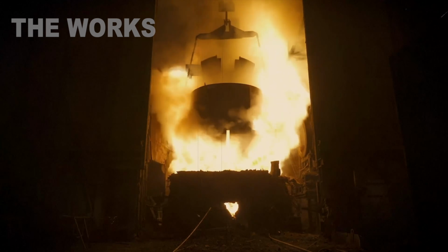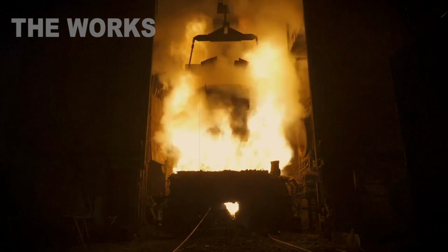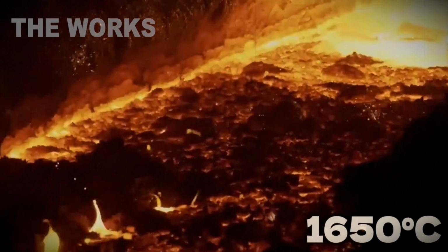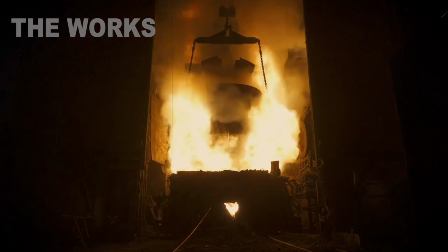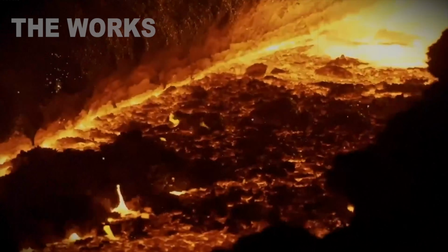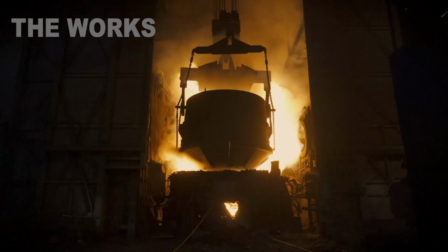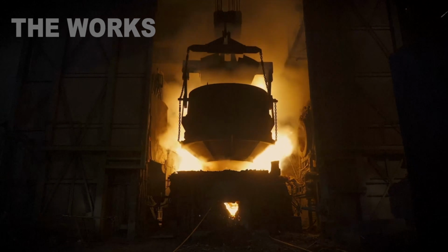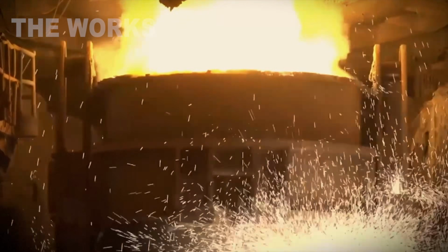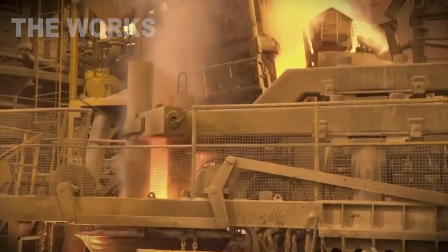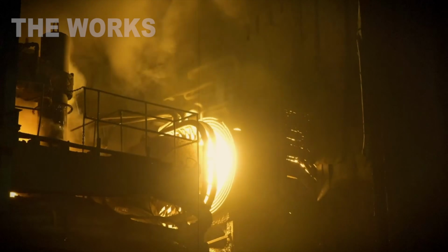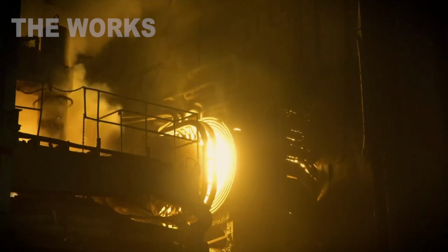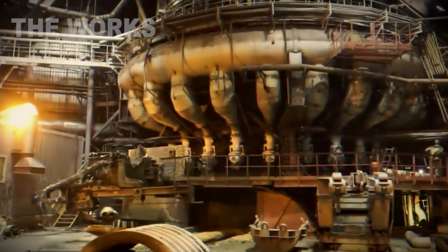Metal melts, becomes a liquid lake. The melt reaches 1650 degrees. Melting time, 3 hours. Lab techs pull samples every 30 minutes. Analyze composition on a spectrometer. Adjust with ferroalloy additives. Precision matters. Carbon tolerance, plus or minus 0.05%. Nickel, plus or minus 0.1%.